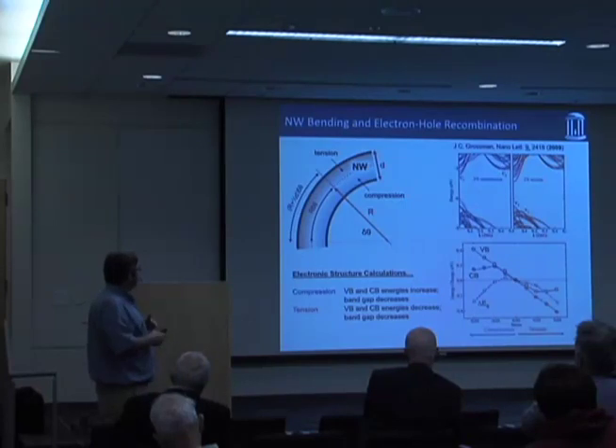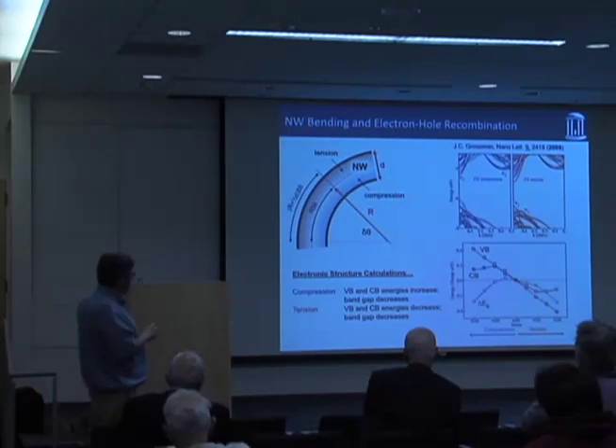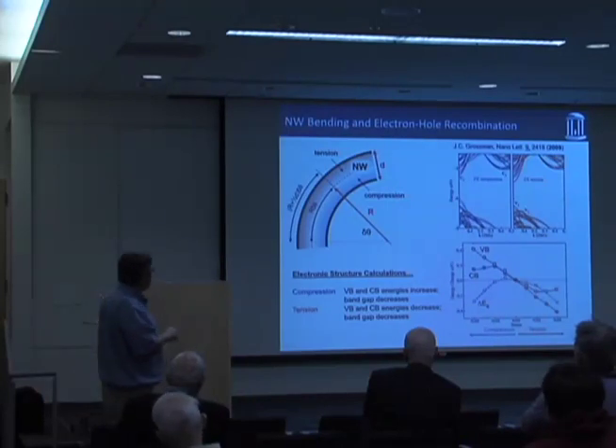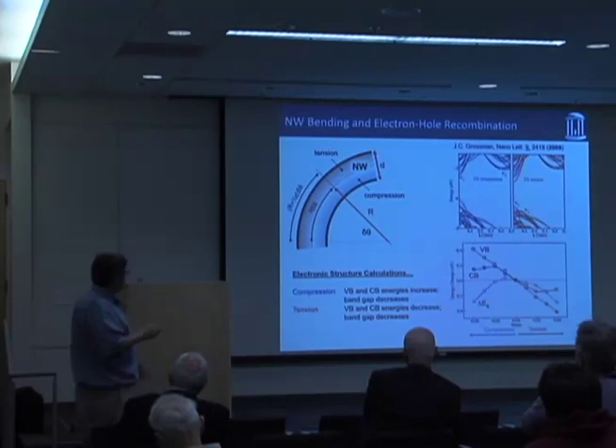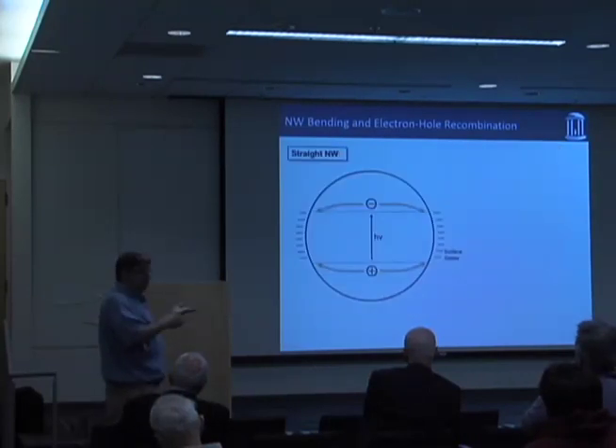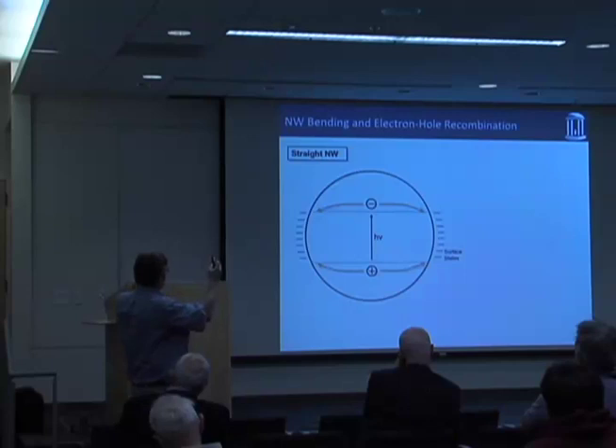What ends up happening is that on one side of the wire, the valence band and the conduction band both go up in energy, but the conduction band goes up less, so the gap gets smaller. On the other side of the wire, they both go down in energy, but the conduction band goes down less, so the band gap gets smaller. And so maybe all we're doing is changing the electronic structure of the nanowire itself. Imagine a nanowire going in and out of the screen. If it's straight, the band is flat across the wire, and there are a series of surface states and so on, and that's going to give me a certain amount of recombination.